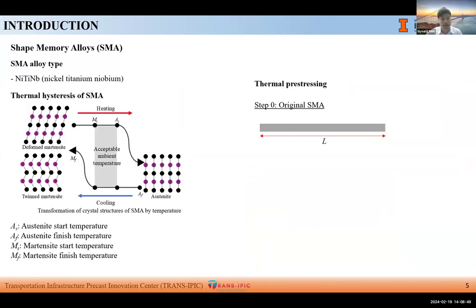In this study, the active confinement effect of SMA as a pre-stressing force was used for crack mitigation. It was thought that replacing steel stirrups with SMA stirrups can relieve crack damage by confining force and even reduce steel congestion by using a smaller number of end region stirrups with larger spacing. Nickel titanium niobium SMA was used for numerical analysis, which has a wide range of thermal hysteresis, resulting in a beneficial effect on application in the civil engineering field.